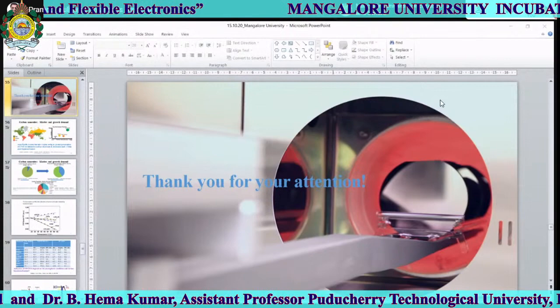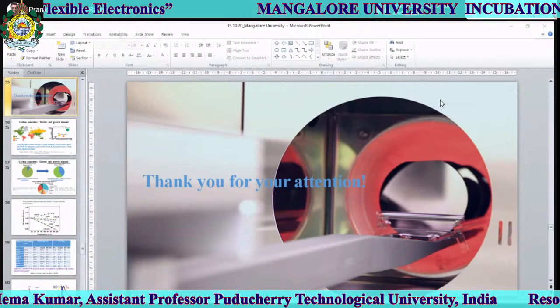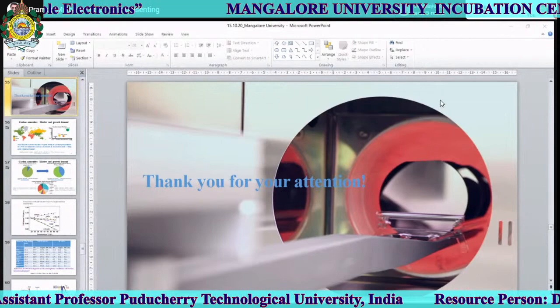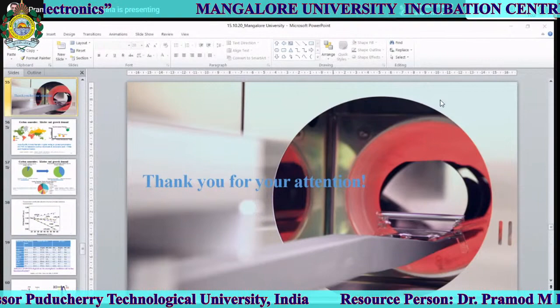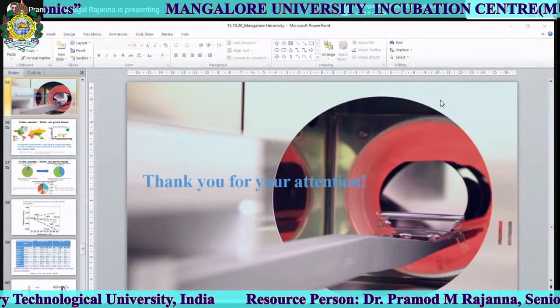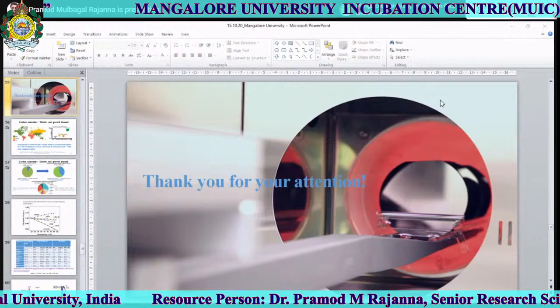I have some question. Is there any degradation effect in your solar cell? We exposed our devices for 2000 hours of continuous exposure under one sun, which is 1000 watt per square meter. Up to 2000 hours it is stable, but after 2000 hours the efficiency reduces by nearly 40%. It decreases from 9% to about 5.8 to 6%, so it's between 5.5 and 6.